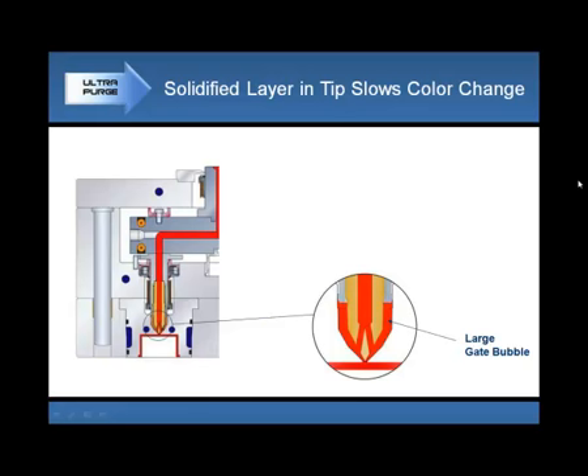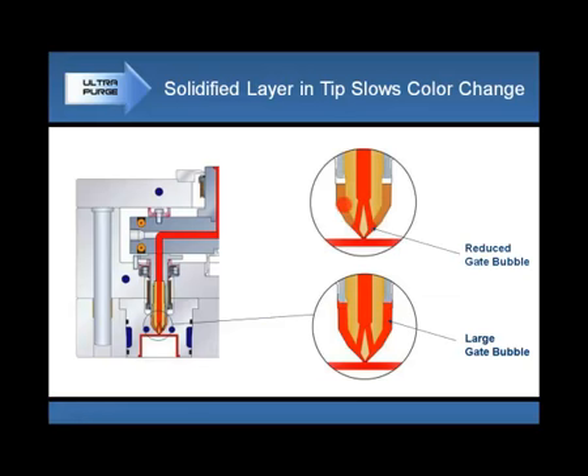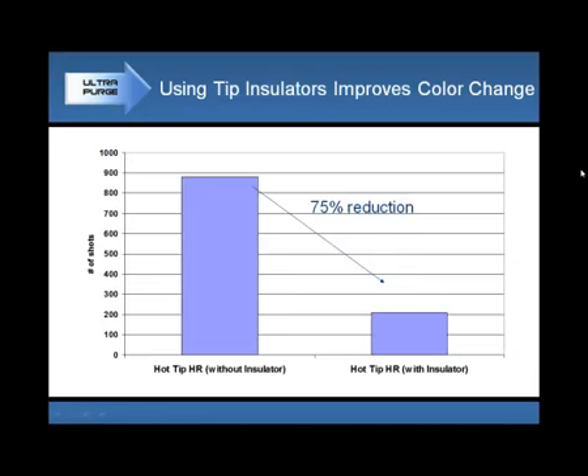As you can see from this picture, this is a very large bubble. When we put a tip insulator, we definitely reduce the bubble area, and that will definitely help us reduce the overall color change. It is proven that by using a tip insulator, we can reduce the overall color change by 75%. It is a huge number just by using a tip insulator.